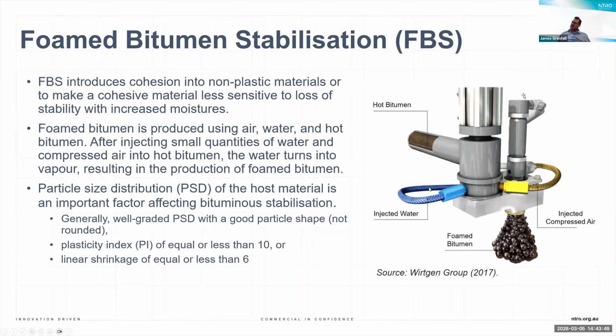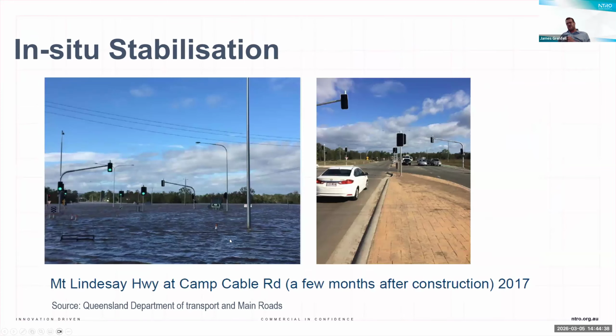So what we're typically doing is passing water through hot bitumen, which foams up the volume by maybe 20 or 30 times for a relatively short period of time. But during that time, the materials are mixed together and the foam bitumen coats fairly well with cold granular in situ host materials, forming lots of little spot welds. We're also adding in a secondary binder, typically in Australia, hydrated lime. The materials are compacted at somewhere between 70 and 85% of optimum moisture content, and they will continue to cure with time to form a very stiff, moisture resilient and also permanent deformation resilient pavement structure.